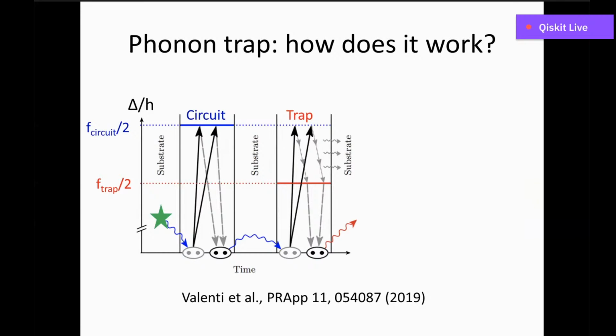First, something can generate phonons in the substrate, as indicated by the green star. No matter what, something can generate phonons. Phonons can then travel through the substrate and reach Cooper pairs in the circuit. If the energy is high enough, they can break Cooper pairs in the circuit and create quasiparticles. The quasiparticles can then recombine and emit a phonon of the same energy.